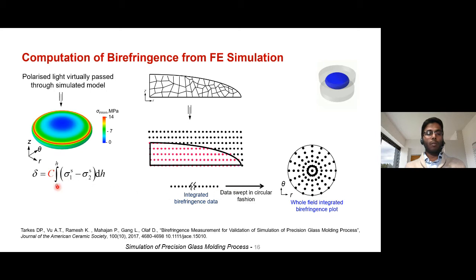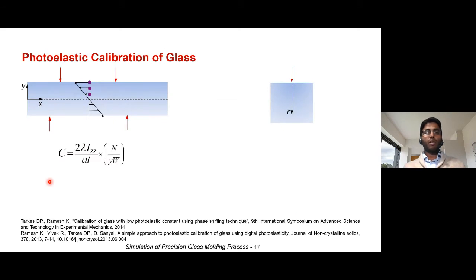We can adapt this procedure over here, but you need the photoelastic constant C for different types of glasses. You need to have a photoelastic calibration step. This was also done experimentally, and here I'm not going to discuss too much detail. In order to calibrate this photoelastic constant of the glasses, we did a 4-point bending experiment for the glasses which had relatively high photoelastic constant, which is easily measurable, and for very low photoelastic constants where the C value is close to 0, that means you will not be able to observe any significant amount of birefringence.